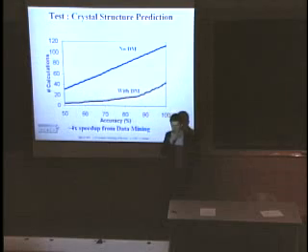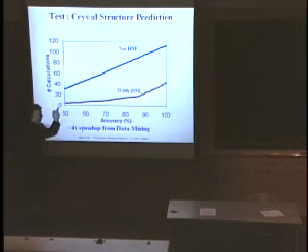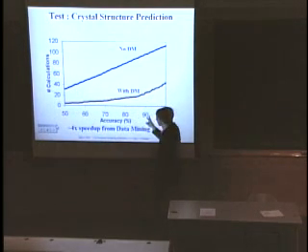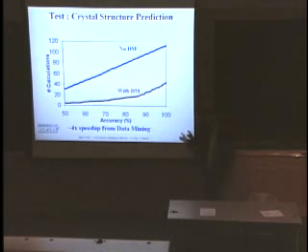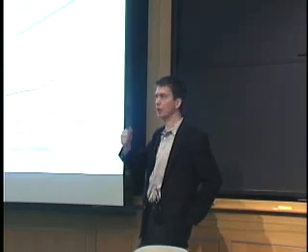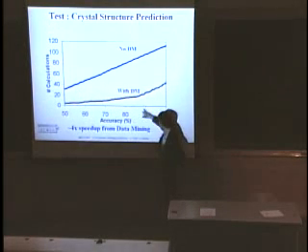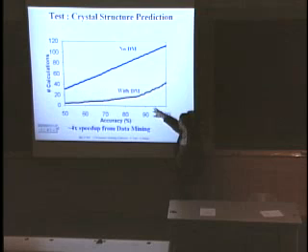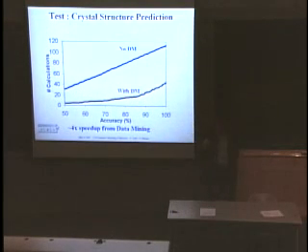This is out of a very large collection of binary metals where we did the test. And this shows how many calculations you need to do to get all the ground state structures in the system with a given accuracy. Because, of course, this is a statistical method, you're never going to get 100% accuracy unless you calculate everything. But what you see is that with something like 15 calculations, you get 85 to 90% accuracy. This is with the data mining technique. So this is an example of building a predictive method without a theory, purely based on statistics.